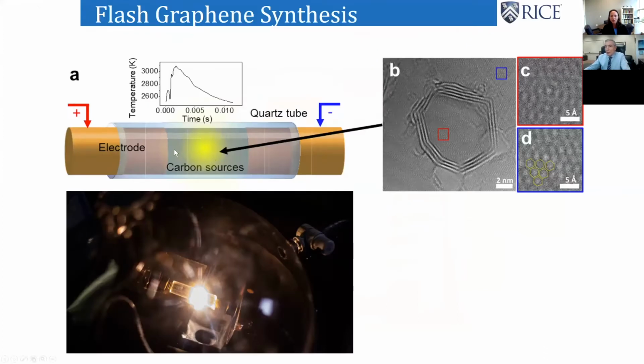What we found is we can take any carbon source and put it between two electrodes, and we apply a high voltage and a high current, and it will break every carbon-carbon bond in the system within about just 2 or 3 milliseconds. It will heat to over 3,000 Kelvin, which is about 2,800 degrees centigrade, in much less than 1 second. And then the bonds reconstruct as the thermodynamically most stable system, which is graphene. It gives a bright flash, so all the excess energy comes out as light. The outer compartment here hardly gets hot at all. It's only warm to the touch because all the energy is concentrated within.